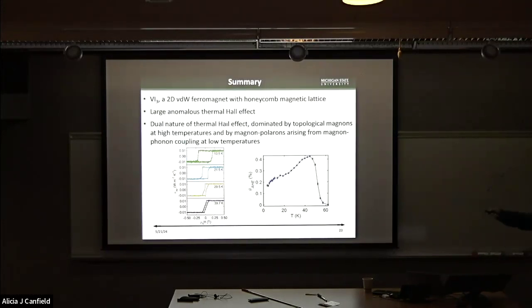Okay, so here's just a brief summary on the vanadium triiodide. We observe a large, anomalous thermal Hall effect, and it has a dual nature. At high temperature it is dominated by topological magnons. At low temperature it is dominated by the magnon-polarons due to the magnon-phonon coupling.